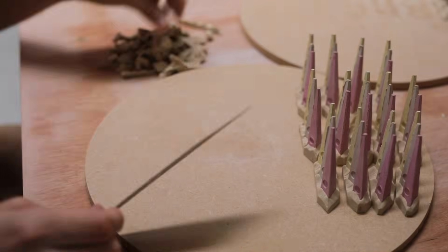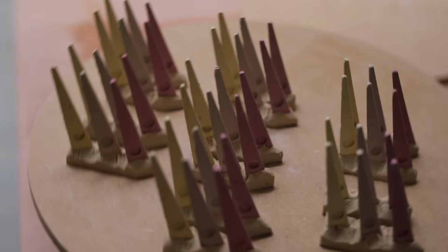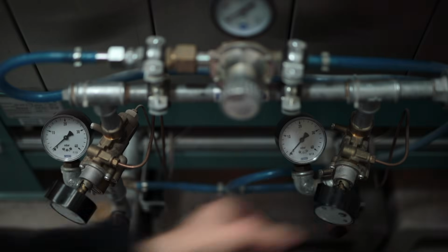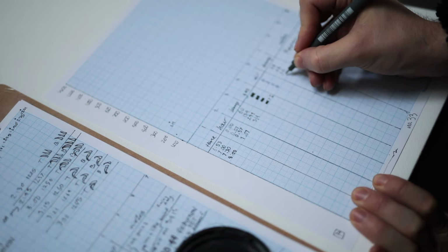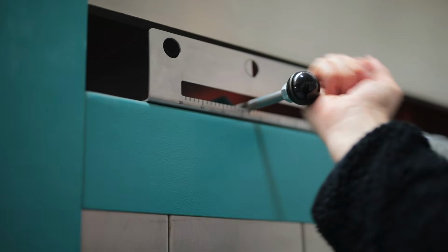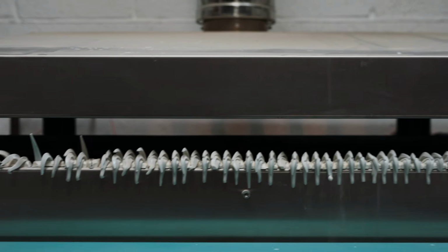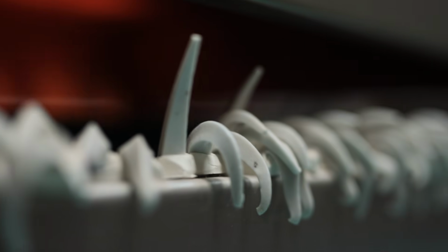And with all the pots and cones packed inside, I'll then gas fire the pots up to 1290 degrees Celsius in a reduction atmosphere, a process that takes about 9 hours from start to finish, and then about a day or so before it cools down to a point it can actually be unpacked. Here are what those cones look like once they've been fired.